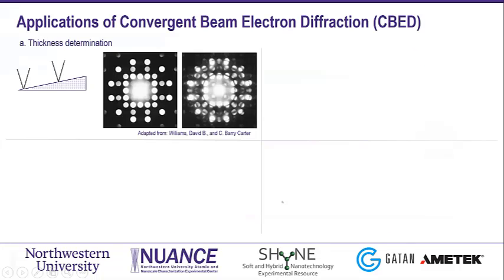So there are a few applications throughout the years that you can see for convergent beam electron diffraction. One easy and direct one is thickness determination, right? As you move from an edge of a sample, for example, you can go for this sort of pattern here, a convergent beam electron diffraction pattern that has more features, and you can use those features to determine the thickness and then later other properties.